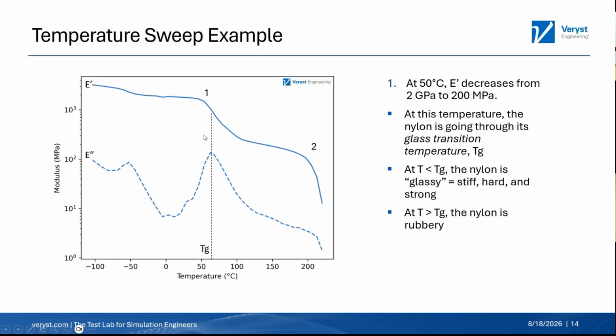And so as we go through this, you can see at point number 1, we have the strong decrease in the storage modulus and this local maximum in the loss modulus. And that's characteristic of the glass transition of materials. And so most nylons have glass transition temperatures in this 50 to 60 C range, give or take. And so you can see actually this happen over the course of this as we heat up the nylon.